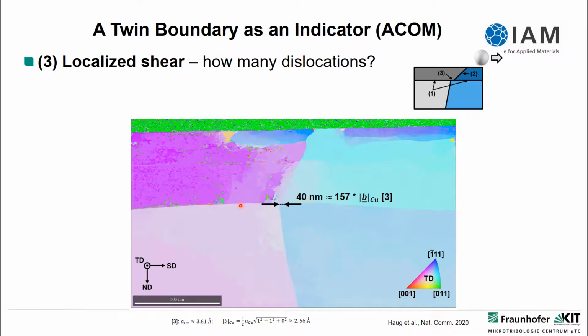Now let's see if those three processes make sense. First, this highly localized shear: we can ask how many dislocations do we need to get this? It's a shift of 40 nanometers, roughly 160 dislocations with a standard Burgers vector for edge dislocation in copper.